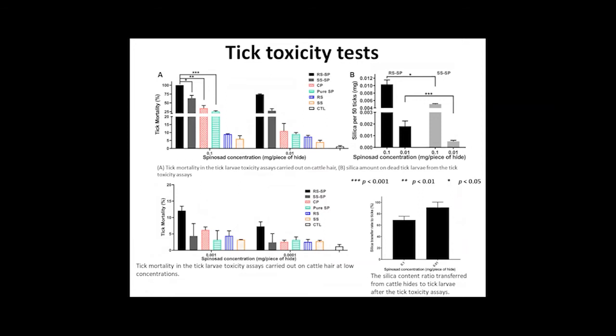At a spinosad concentration of 0.1, spinosad with a rough surface achieved a high tick mortality rate of 99.9%, surpassing the performance of the other three samples. At lower spinosad concentrations, spinosad with a rough surface can maintain its high tick mortality, while the mortality rates of the other spinosad formulations had largely decayed. The tick toxicity result indicates the advantage of the rough surface nanotopography of the rough spinosad formulation.